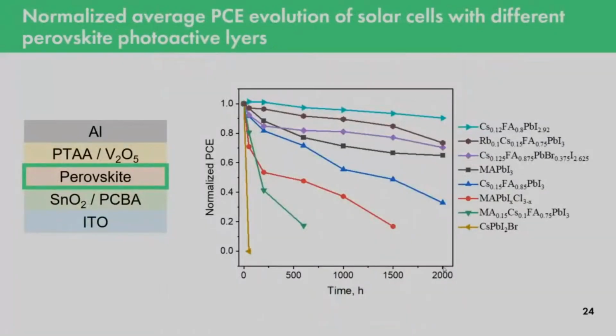So we decided to check all of our materials also in completed perovskite solar cells and compare them. And as was consistent with atomic force microscopy, the best material was cesium formamidinium lead iodide with the excess of lead iodide. So probably the excess of lead iodide shifts the balance in the perovskite degradation towards the initial perovskite structure from the degradation products, as was observed for photodegradation experiments by our colleagues and by different researchers. The second place belongs to rubidium-containing perovskite, and unfortunately, the bottom, as was probably expected, was for the inorganic material and methylammonium-containing materials also.